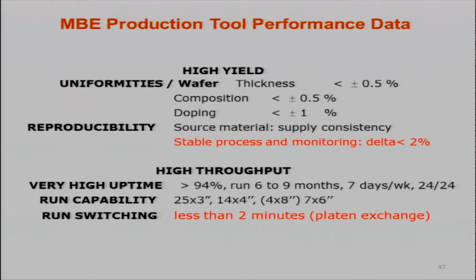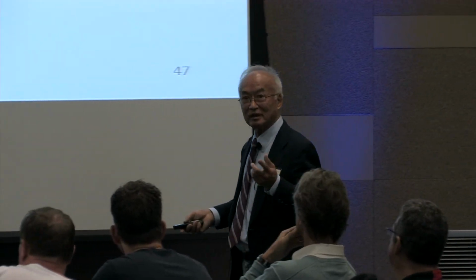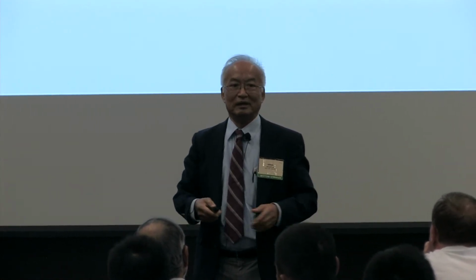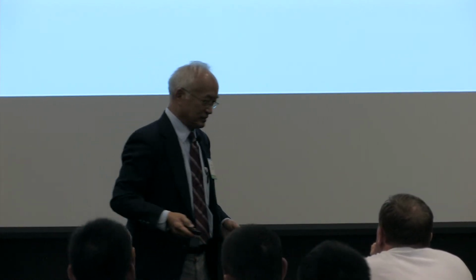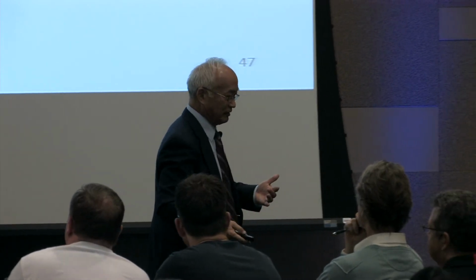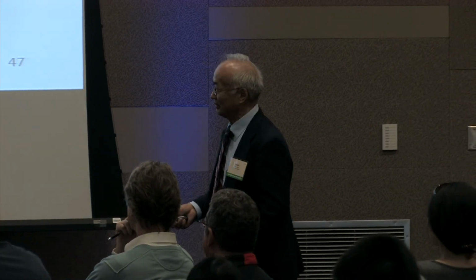And then large platen, these days you can have 25 3-inch wafers mounting on each platen. And then you can mount 7 6-inch gallium arsenide wafers on each platen. Furthermore, the changing time from platen to platen only takes 2 minutes. Now, this is extremely important. As you know, our competitor, MOCVD, is constantly eating our lunch, and the changing of platen to platen in MOCVD is a lot longer. And of course, there are many other advantages of MBE versus MOCVD; they of course also have their advantage over MBE, which is another topic that we can talk about.